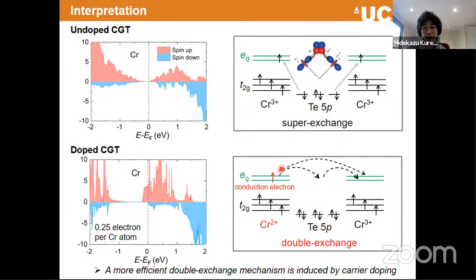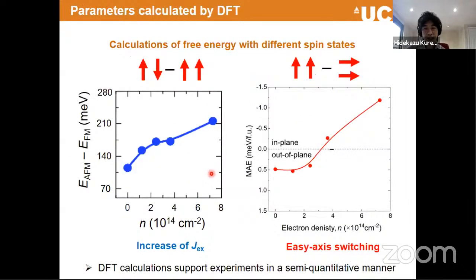And in particular, when we have an alignment between the conduction electrons and the local ion moments, then this electron can further delocalize, and it can gain the kinetic energy. Therefore, that can give us an additional driving force to form the ferromagnetism. So that's the intuitive picture of why, when doped, CGT becomes a relatively high temperature ferromagnet. To support that, we also did DFT calculations, and what I show here is the energy difference between the antiferromagnetic state and ferromagnetic state. Subtracting these two states can tell us something about the exchange energy. In line with our experimental results, when we dope electrons, we can really increase the exchange energy. Therefore, we can get the large Curie temperature.